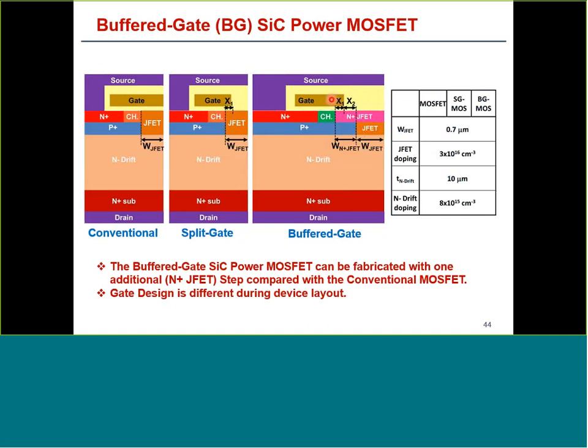By doing that, we get exceptionally good shielding of the gate from the drain, or buffering of the gate, and that significantly reduces the capacitances as well as the gate charge. Now, one of the things that you have to watch out for when doing this is that if you don't enhance the doping in this portion here, then the built-in potential of the p-n junction will deplete this part, and you will end up with very high on resistance. So we had to introduce an additional JFET doping to achieve proper functionality.